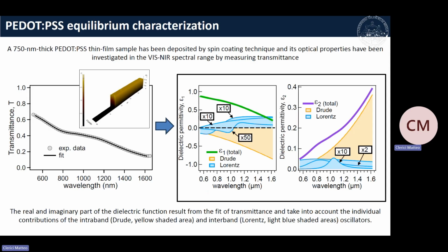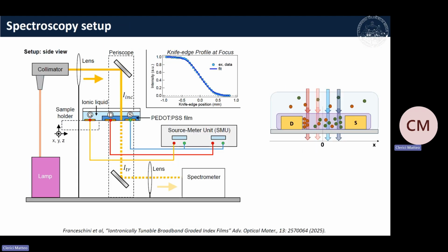We measured the transmission first at equilibrium without voltage applied. We extracted the real and imaginary part of epsilon. Then we applied voltage in different configurations and probed different regions of the channel to see how the transmission would change, so we could infer how much the refractive index has changed. We had a 2 millimeter channel, and our spot size was about 500 microns, so we had 4 discrete spots.